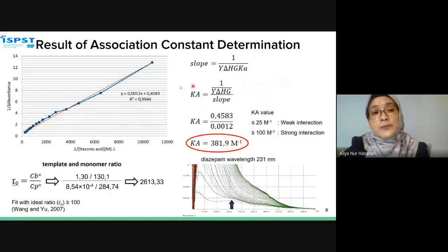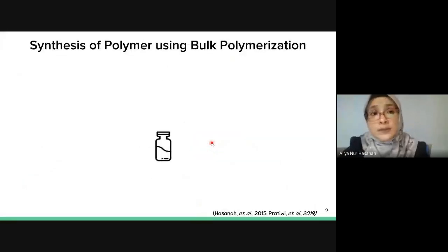This is the result of the association constant determination, and we find that the Ka value for diazepam and itaconic acid is 381.9 per molar. So according to Wang and Yu in 2007, this value is categorized as a strong interaction. For the synthesis of the polymer, we are using bulk polymerization.